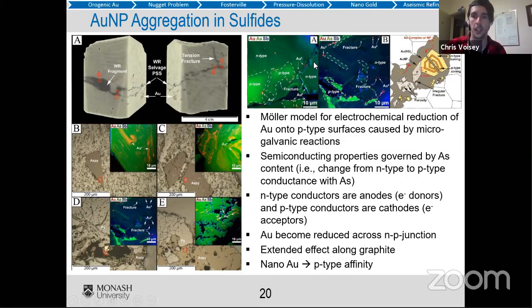And we looked at where gold was hanging out, and gold would normally drop out not only in fractures, but it would hang out in fractures next to P-types. So that would mean that if gold exists as a gold nanoparticle, it would stick to P-types, of course. And then along these NP junctions is where they become reduced. So if gold is existing in these sort of intergrain boundary solutions, then you could reduce it by having this contrast in sulfide conductance type.